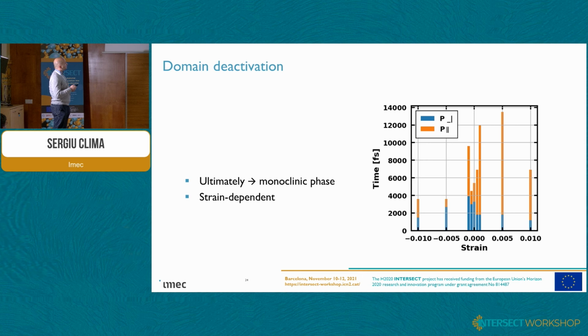And then at the end of the orange bar, it switches into the monoclinic phase. As you can see, when we apply a compressive strain, the perpendicular polarization is more or less on the same timeline, but the parallel to the surface lifetime of the polarization is much shorter than in the case of the tensile strain, and then afterwards it goes directly into the monoclinic.